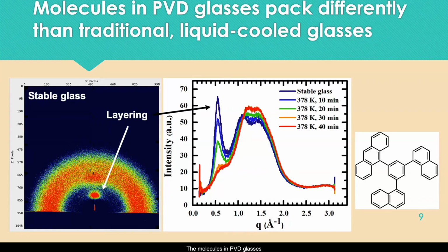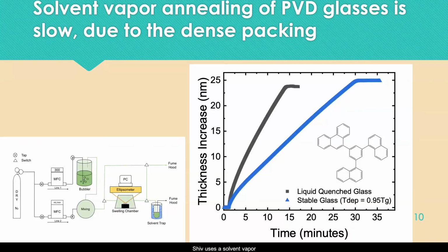Molecules in PVD glass are packed differently than in traditional liquid-cooled glasses. Lexi looks at this using X-ray scattering data, and she sees a layering peak indicative of stable glasses that disappears upon annealing. Shiv uses a solvent vapor annealing system under ellipsometry to look at the solvent vapor annealing of PVD glasses and sees that it's slow relative to liquid quench due to the density of packing.